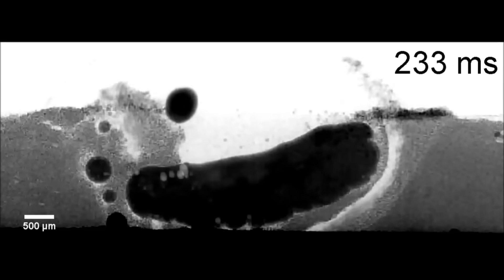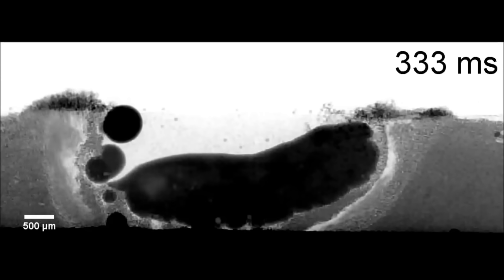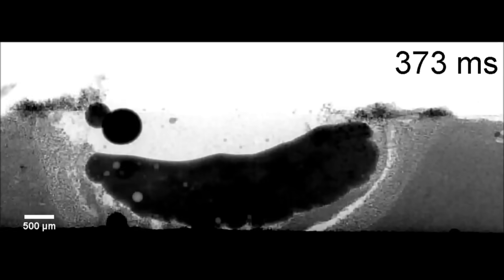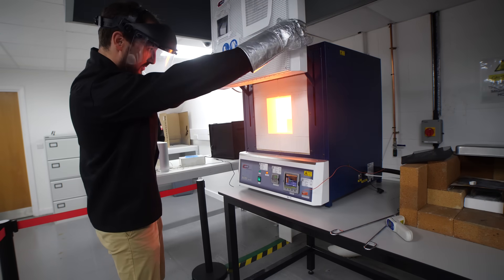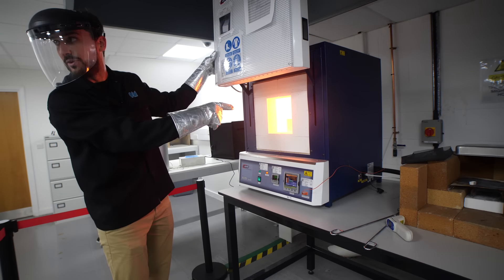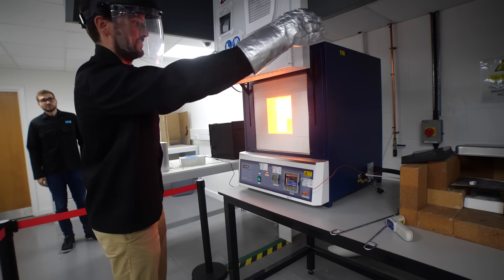In another experiment they investigated the interaction of two melt tracks. Here you can see more pores forming as a result of overhangs trapping gas, and yet more pores form in the same manner as before as we reach the end of the track. Clearly, this process is much more complicated than just melting some metal powder together, and in the end the final products that come directly out of a 3D printer are far from finished and need a significant amount of post processing.